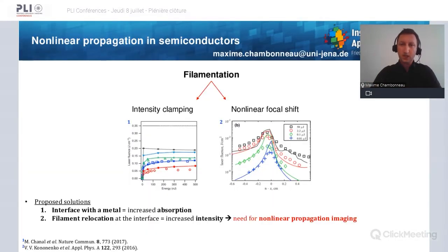So why? Well, I gave partly the answer in the beginning of my talk. Everything originates from the filamentation during the propagation through silicon, leading to both an intensity clamping and a nonlinear focal shift. So here are the two solutions we propose. For the intensity clamping, we propose an interface with a metal in the frame of semiconductor to metal laser welding, meaning that the absorption is increased, which is actually what we aim for. And second, for solving the nonlinear focal shift, we propose a filament relocation at the interface between the two materials, meaning that the intensity should be increased.